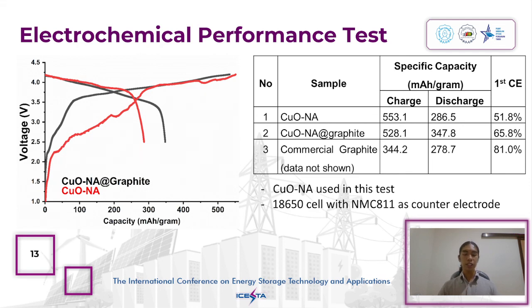Based on the discharge capacity, the highest capacity was established by the copper oxide and graphite composite. The sample with copper oxide anode has low initial coulombic efficiency due to the irreversible process in the initial charging process. Thus, it can be concluded that by compositing copper oxide with graphite, the discharge capacity of the cell is far superior, and thus the overall performance of the cell is enhanced.